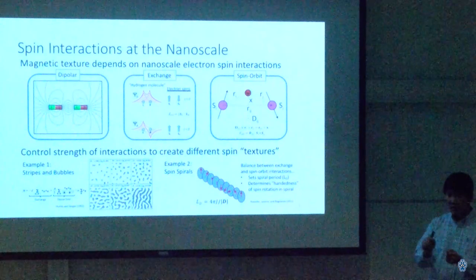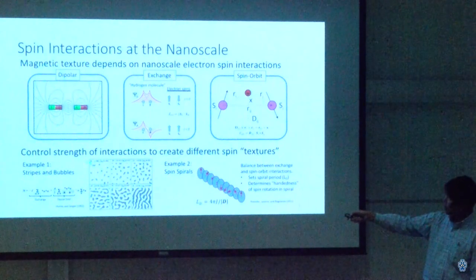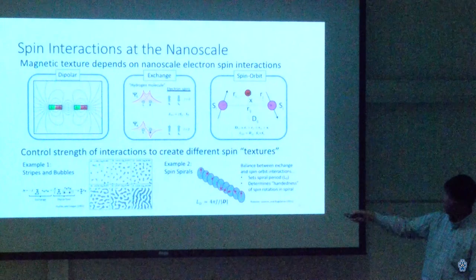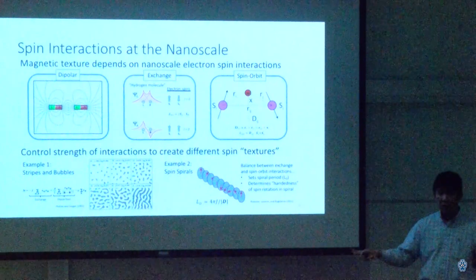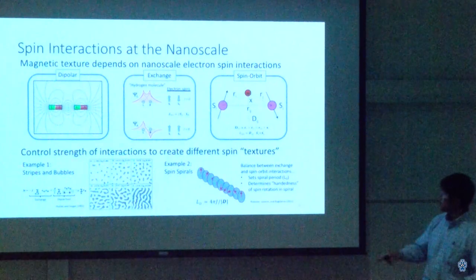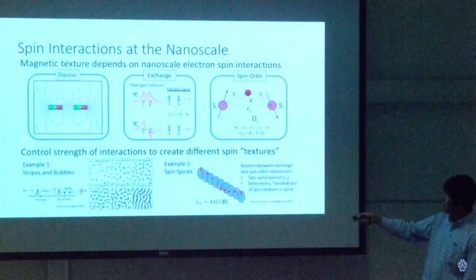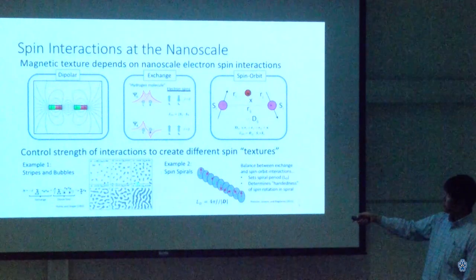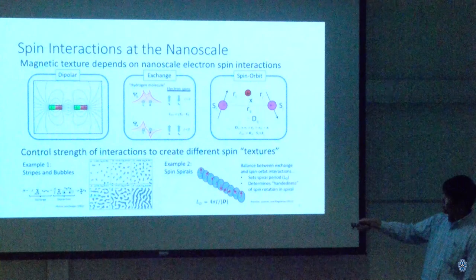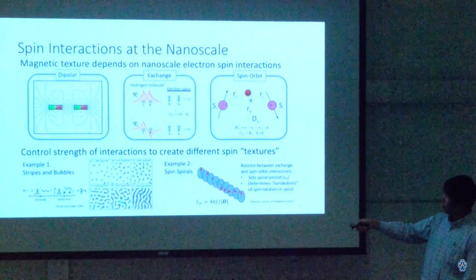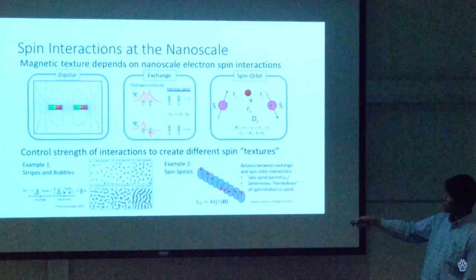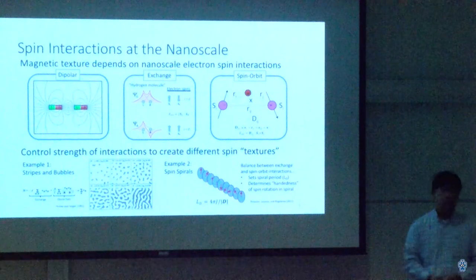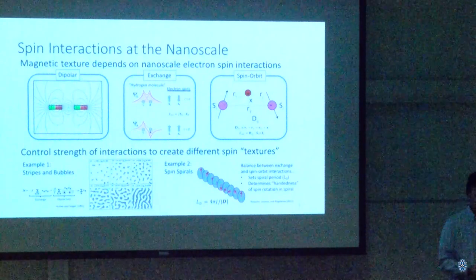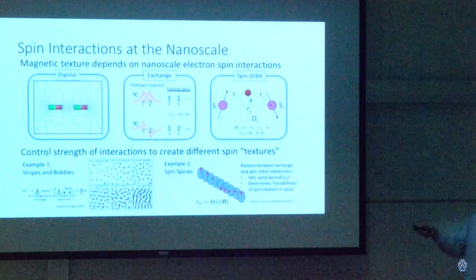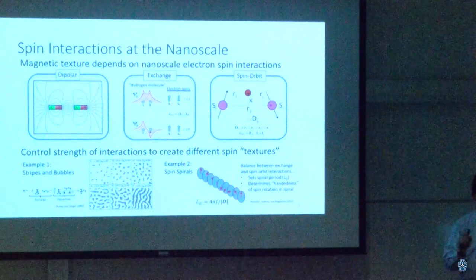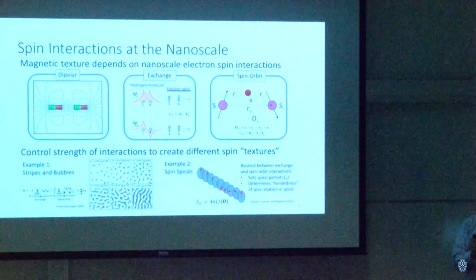And if you twiddle one knob more than the other, you can get what are called isolated bubbles, or little patches of up contrasting with the down background, to an environment in which the bubbles are very densely packed to the point where the bubbles begin to elongate and create stripe-like domains, a lot like what you saw in yttrium iron garnet in the previous slide. So that's just dipole and exchange and changing the relative strengths of those two.